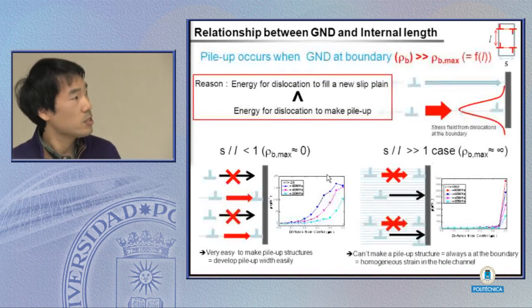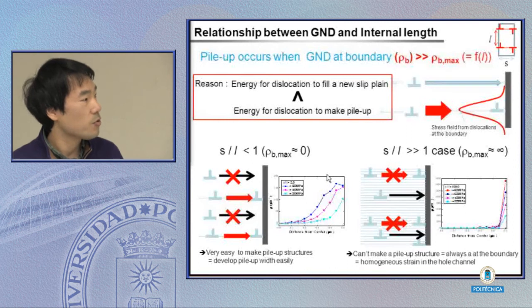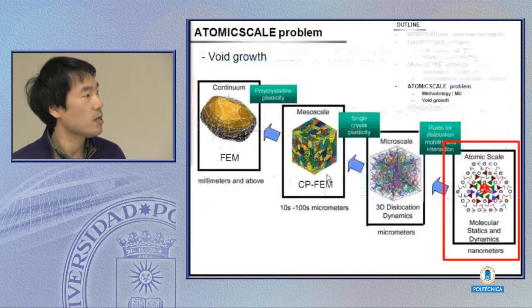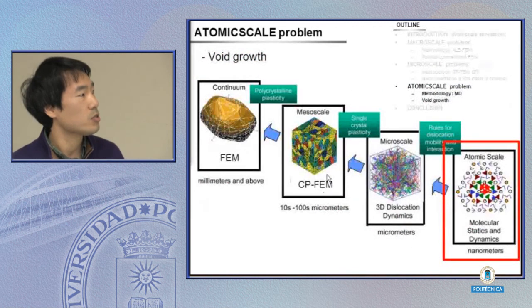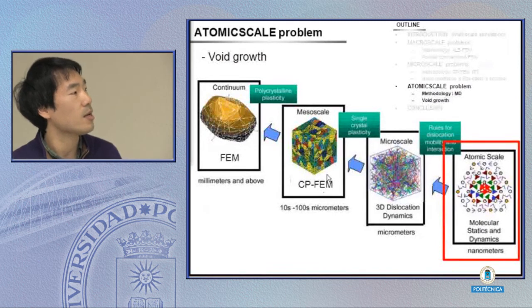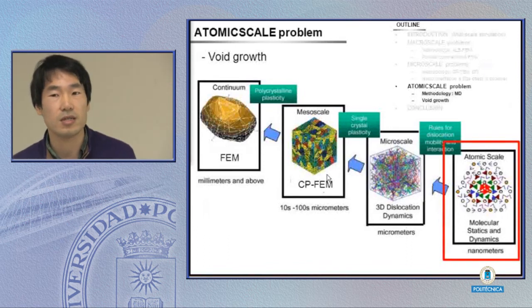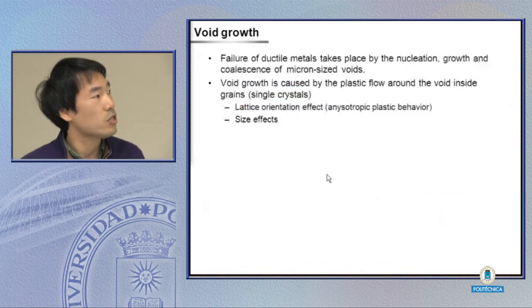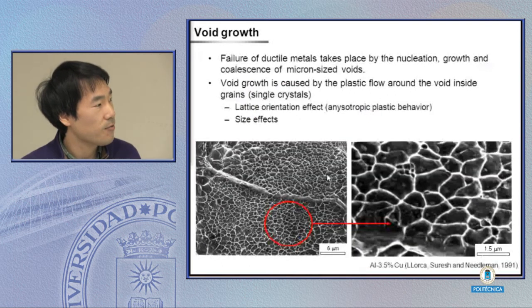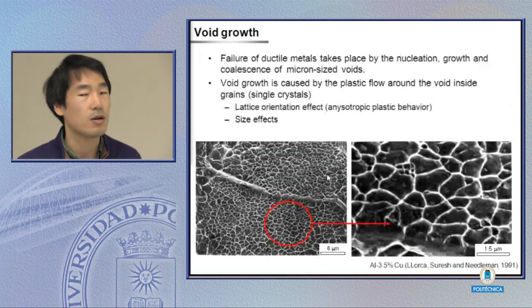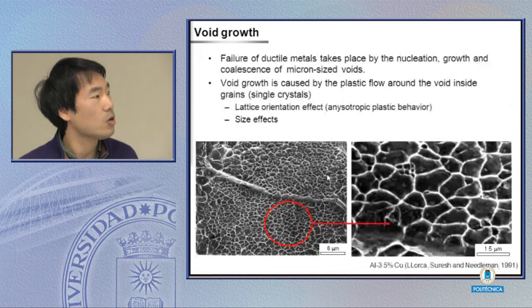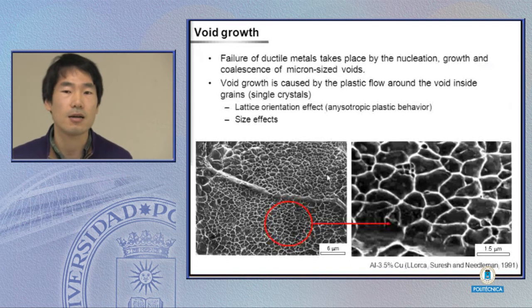In this case, when the ratio is very small, it means that there are few sites at the boundary. So dislocations easily fill all the sites at the boundary and start to make a pile-up from the beginning. On the other hand, when the ratio is very big, it means that there is infinite space at the boundaries. So dislocations always fill the empty space, not making a pile-up.